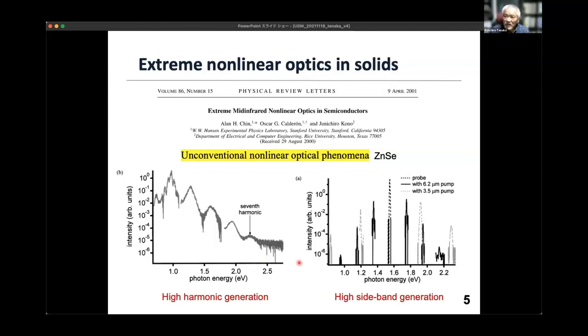They also reported high sideband generation. In this case, in addition to the mid-infrared laser, they also used a near-infrared laser, and they observed this kind of sideband around the near-infrared laser light. This is also a very non-perturbative phenomenon. But at the time, they did not show the power dependence and other things in detail.